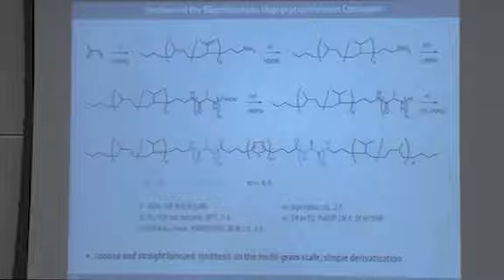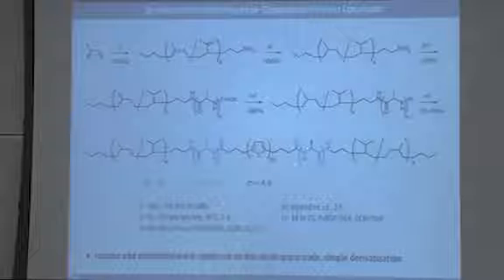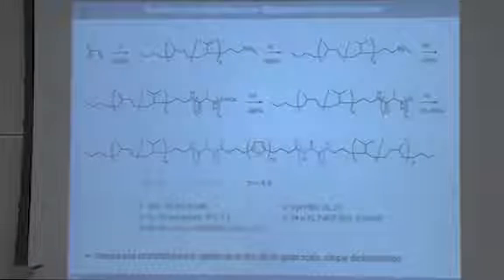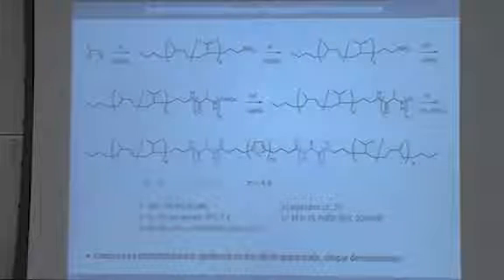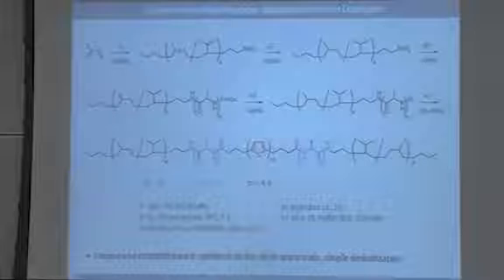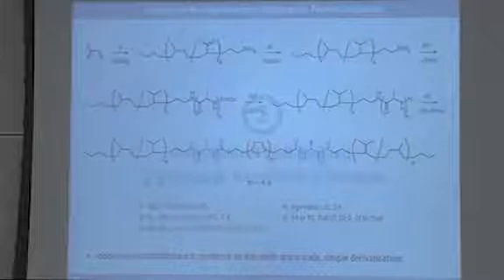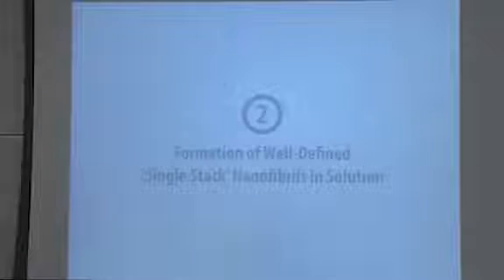And so I think that this is just a neat trick that made our whole synthetic pathway very, very convenient to pursue. Then we take these building blocks, for example, an oligothiophene dicarboxylic acid, and just link it in a final peptide coupling step to an oligopeptide that we deprotected on the amine side, and we're done. And so as you can see here, we took the molecular parameters we previously determined and transferred them onto this molecule. We still made a series of different molecules with differently long oligopeptide segments just to see what would be the effect on the self-assembly.